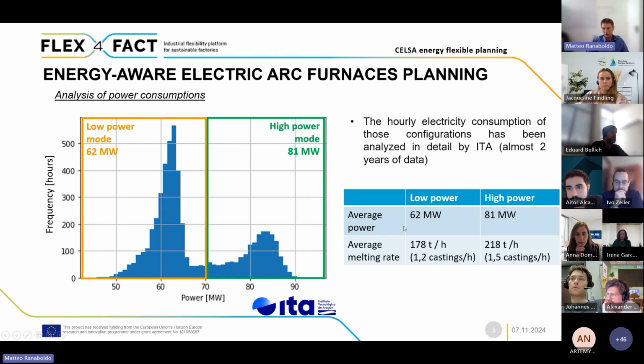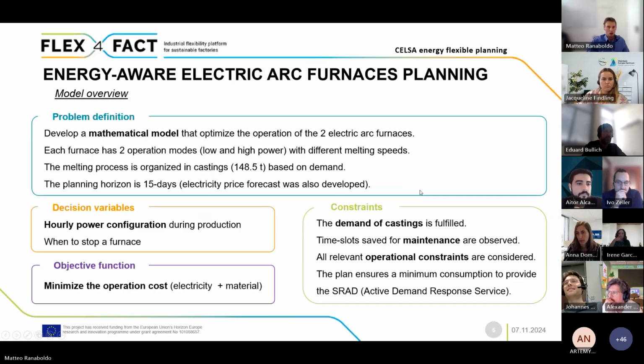And clearly, the higher the power consumption, the higher the melting rate. Here we are visualizing the melting in tons per hour or castings per hour, considering that one casting is 148 tons. Starting from that, we developed a mathematical model, an algorithm, with the aim of optimizing the operation of those two electric arc furnaces that, as we say, each has two operation modes with different melting speeds, knowing that this melting is organized in castings and that the planning horizon is 15 days. In parallel, we also developed an electricity price forecast algorithm in order to estimate the price for the next 15 days.